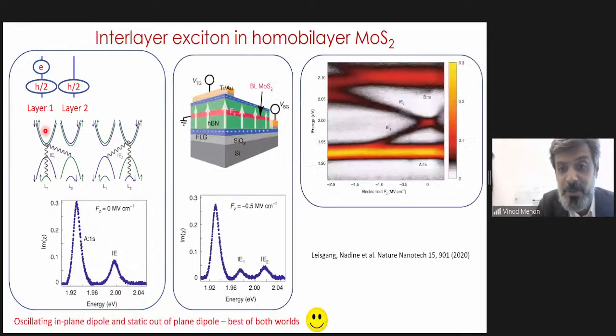But it turns out in 2D materials, if you just take two layers, it's a bilayer. So instead of the monolayer limit, you go to the bilayer limit. It turns out in a bilayer molybdenum disulfide, there is an interlayer exciton that gets formed. So this is my layer 1 and this is my layer 2. And you get an exciton that is formed between the two layers where the electron sits in one layer and the hole sits in the other layer. And the hole is actually shared between the two layers in some sense. And what happens then is you get this interlayer exciton, which has a permanent dipole moment, and in fact, you can apply an electric field and you can move these interlayer excitons.